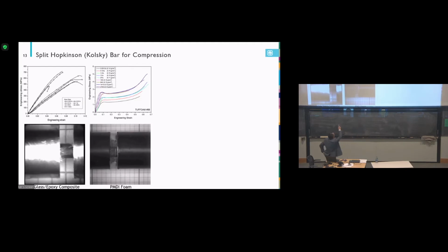Now you can see from that, we tested different strain rates. You can see for the composite, the modulus keeps increasing with the strain rate, and the plateau stress keeps increasing with strain rate. That's what we call the strain rate effect, which means usually a material becomes stronger when you hit it harder.